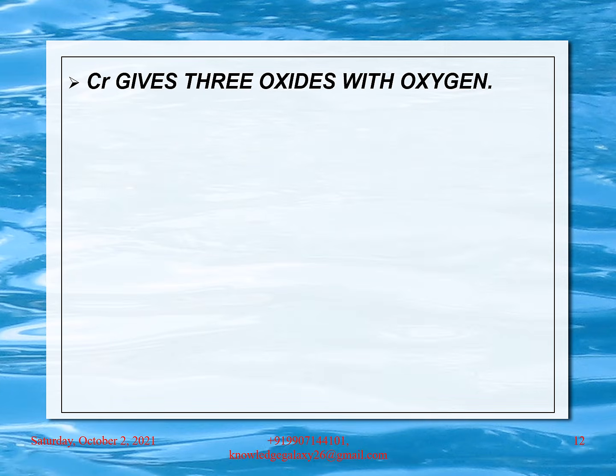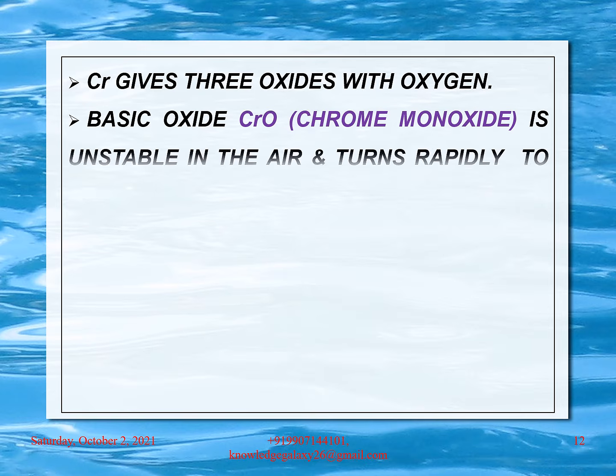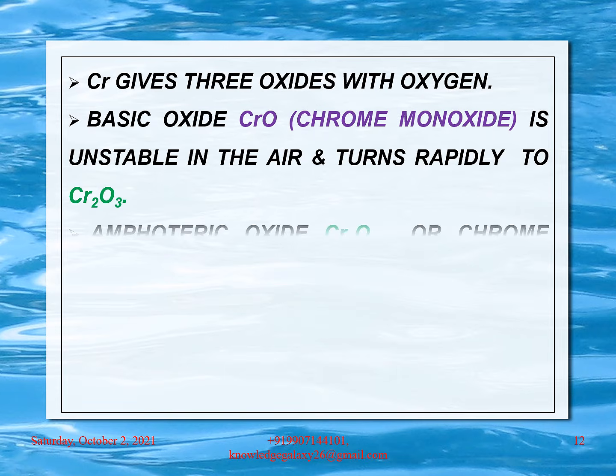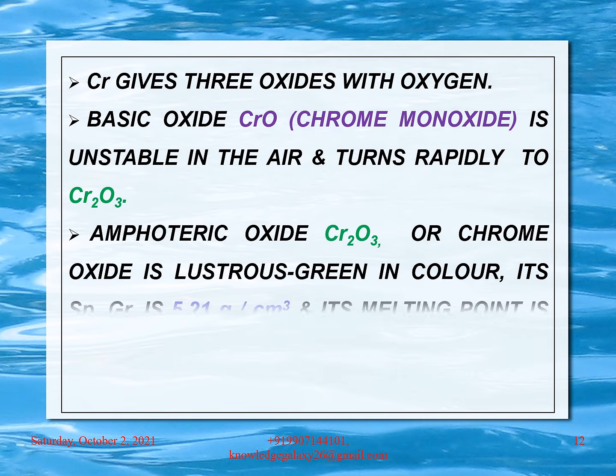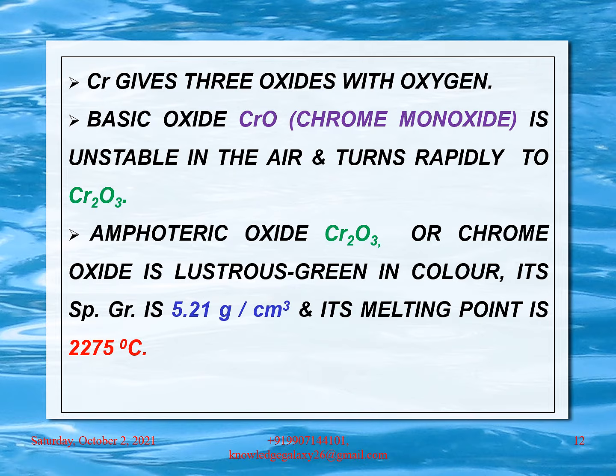Chromium gives 3 oxides with oxygen. Basic oxide CrO, that is chrome monoxide, is unstable in the air and turns rapidly to Cr2O3. Amphoteric oxide Cr2O3 or chrome oxide is lustrous green in color. Its specific gravity is 5.21 gram per cubic centimeter and its melting point is 2275 degrees Celsius.